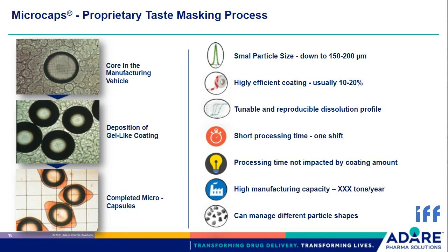Processing time is relatively short, one shift, one batch, and it also has high manufacturing capacity. For instance, in the case of potassium chloride microcaps, last year we produced more than 800 tons of processed material. It's also able to manage non-ideal particle shape thanks to the flexibility of the coating during the process, and we can also process micronized material using controlled aggregation, and you will see an example later on.